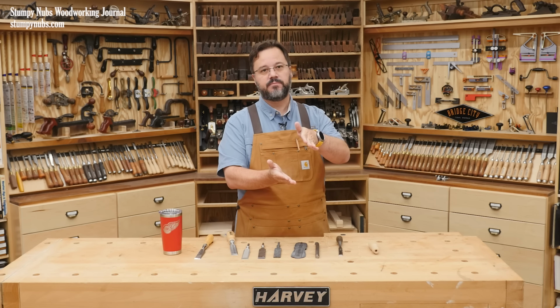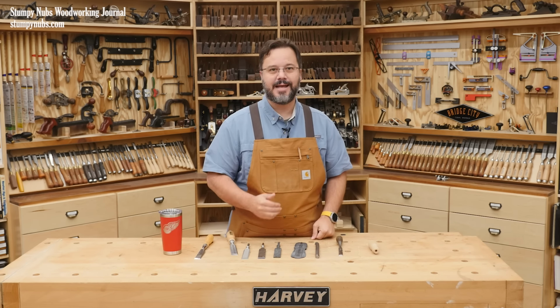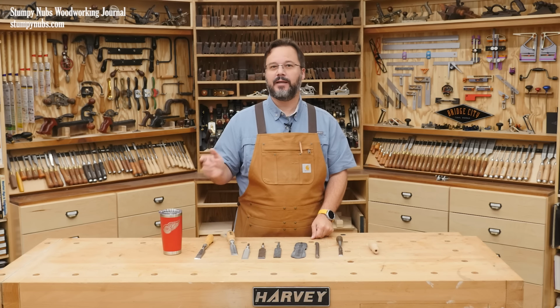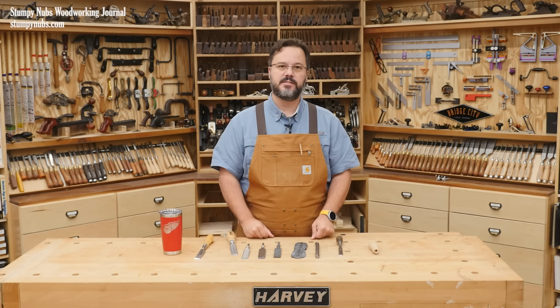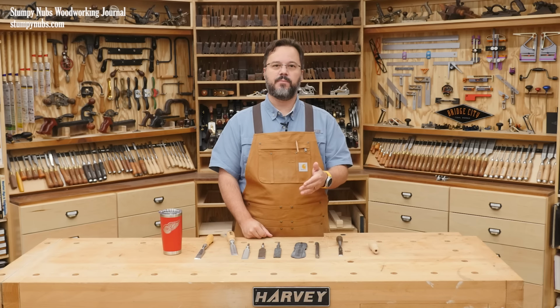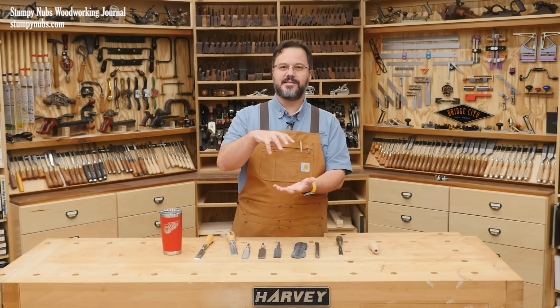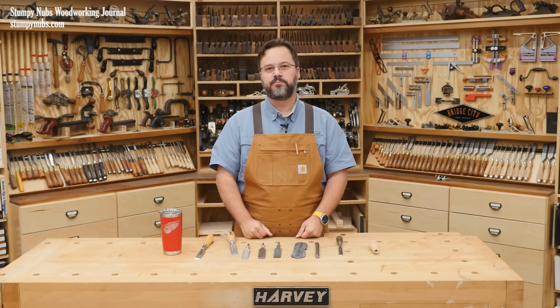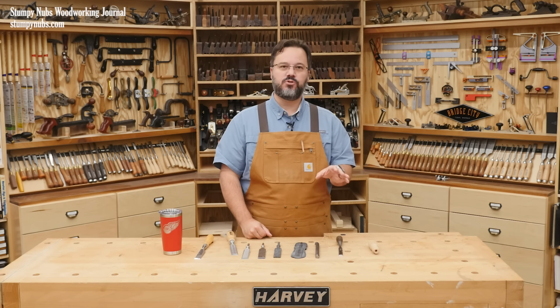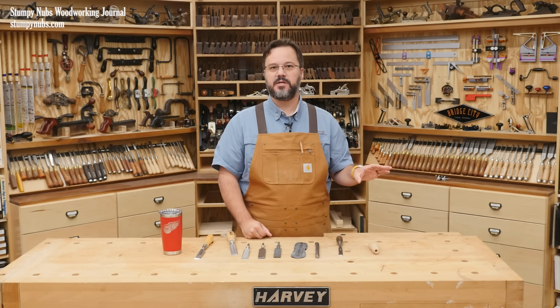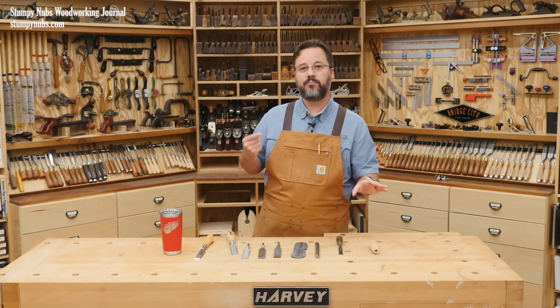throughout its thickness. This is called sheared steel, and it was a great improvement in tool making, but it was still very inconsistent due to the uneven distribution of the carbon, especially in the old days before additives were found to help those gases seep deeper into the iron. Shear steel was used in some tool making well into the 1800s,